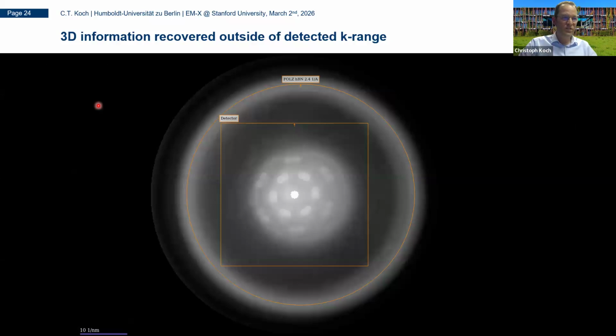But before I come to that, let me also show you the diffraction pattern that Anton, that's basically the PhD student who has performed this work, has now carried out on these 3D reconstructed potential slices. Because we have the potential slices, we can now also run any other multi-slice simulation through it. So now producing a multi-slice simulation with a convergence angle of only 3 milliradians, so that the disks, these Bragg disks, don't overlap. You can now really see also the diffraction pattern. You can see again this twist angle. But what you can also see, you can see the higher order Laue zone.